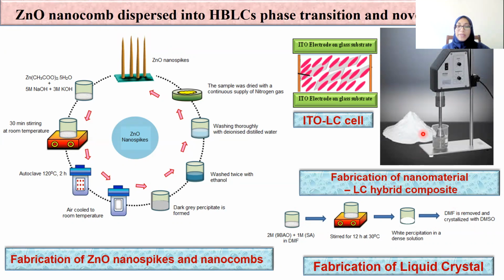Then for the synthesis of nanomaterial dispersed liquid crystal, a typical amount, that is around 0.35 gram of zinc oxide nanocombs, is mixed with 0.005% of pure liquid crystal suspension. It is then continuously stirred for an hour, which is then followed by ultrasonic vibration that enables the nanomaterial to be completely dispersed in the liquid crystal material. The obtained nanocomposite is then vacuum dried at 50 degrees centigrade for about 2 hours.